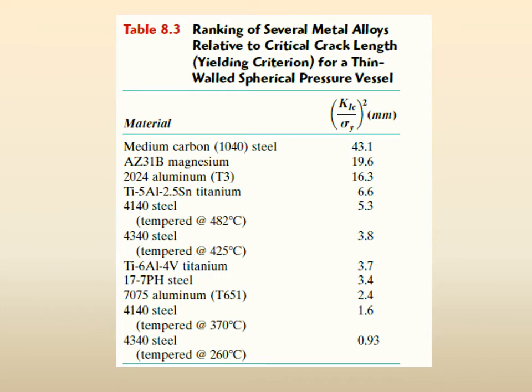We are showing some of those materials: medium carbon 1040, magnesium alloy, aluminum alloy 2024, titanium alloy, 4140 steel, 4340 steel, and so on. And of course 4340 steel tempered at 425, tempered at 260, different temperings. Each time from the previous table, you are taking K1C upon sigma y in megapascal units and comparing this square. So this value will represent the crack size.